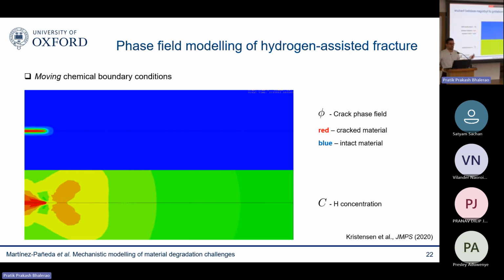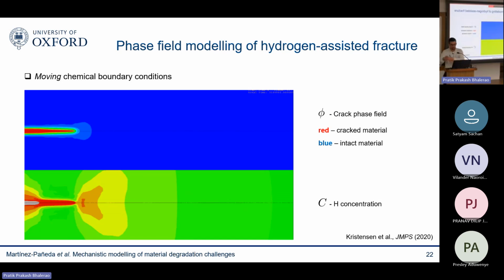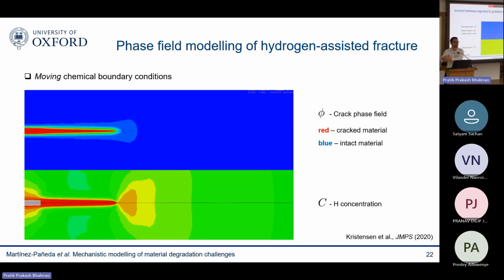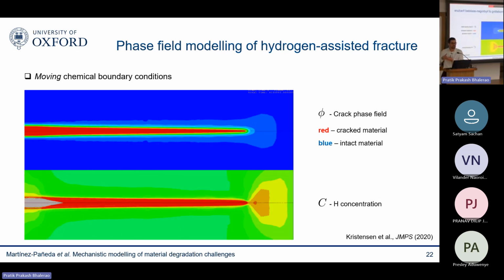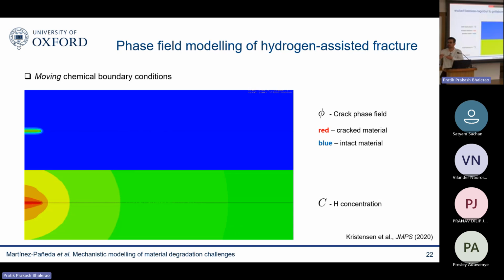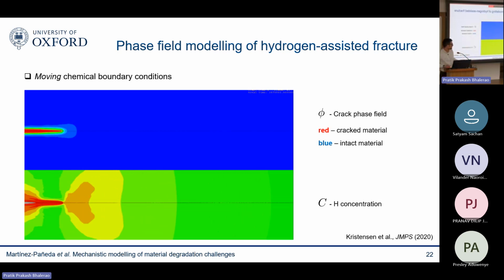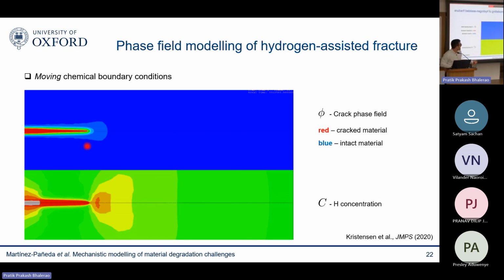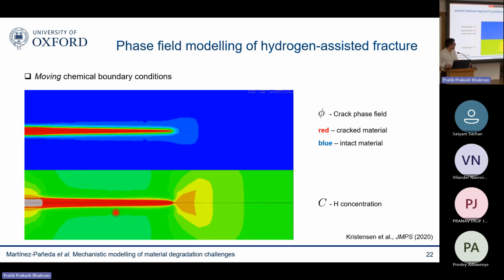If you imagine that you have a pipeline in seawater or in hydrogen gas, the moment the crack propagates, the fluid is going to immediately occupy that space. It's going to immediately come into contact with the newly created crack surfaces. So you can do that. On the top, you see the phase field growing, and here you see the hydrogen concentration. You can see, by the way, how eventually it accumulates also near the crack tip, near the hydrostatic stress field. But you can see how, as the crack propagates, the hydrogen environment can follow.